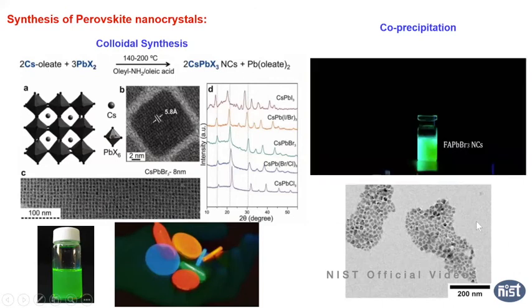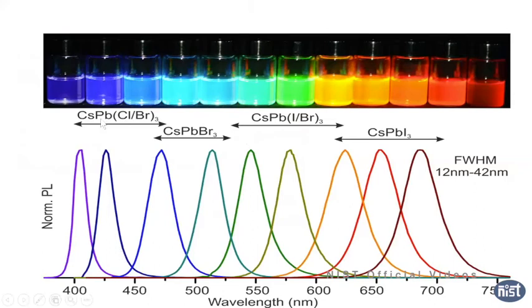And this is just how perovskite is synthesized. It's one kind of synthesis. You can see it is a very fast synthesis. It's not very homogeneous, but it's very bright. That's because the absorbance and other properties are very strong compared to colloidal quantum dots like chalcogenide quantum dots. And you can also get very bright emission across the full visible window.